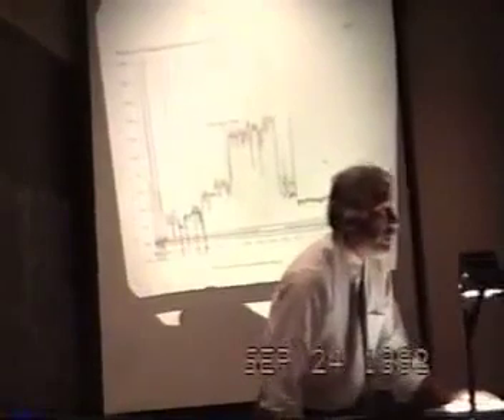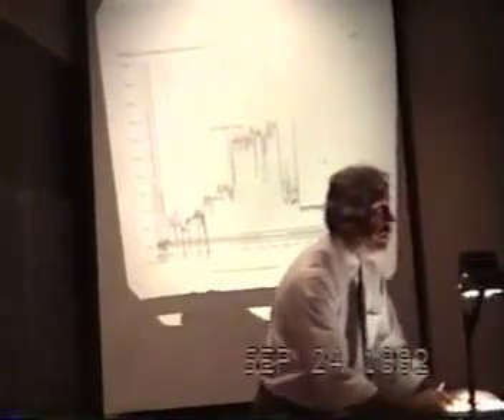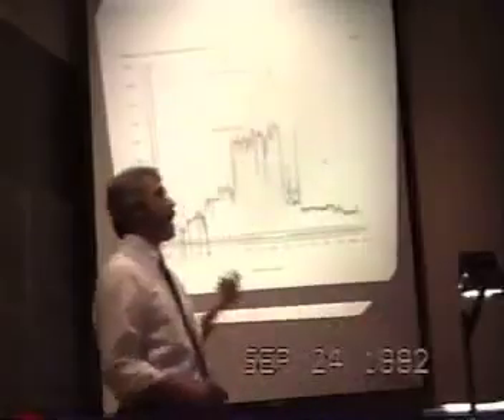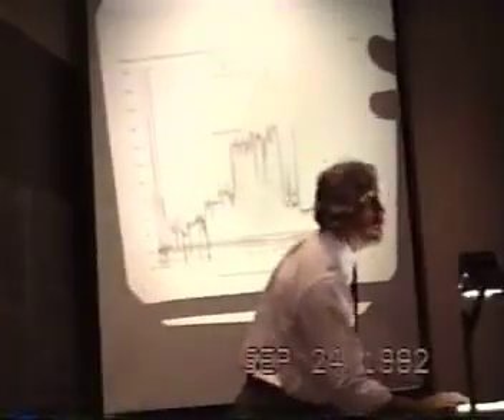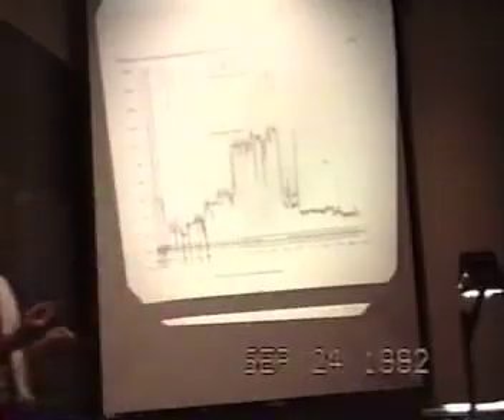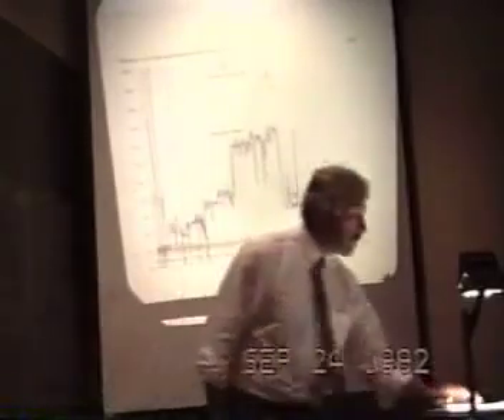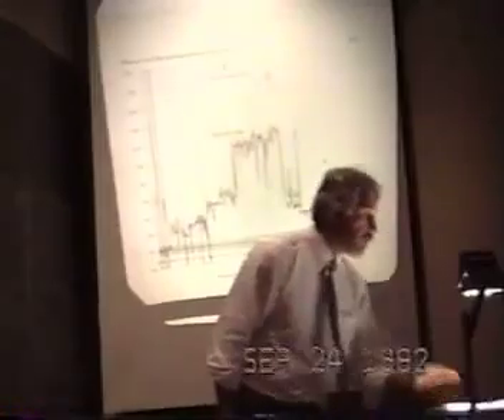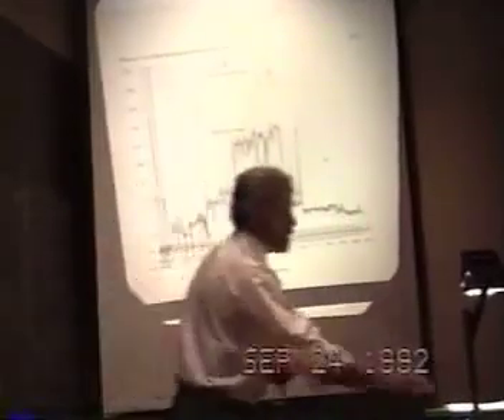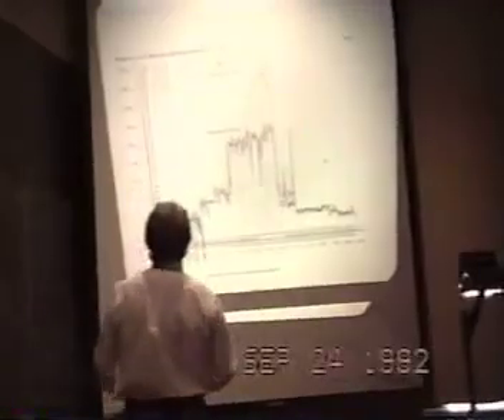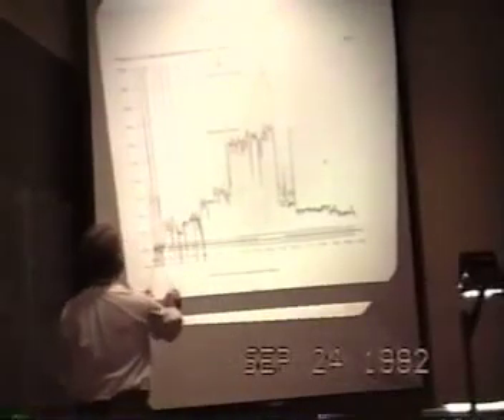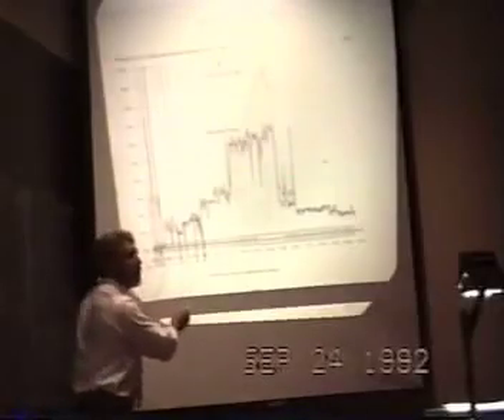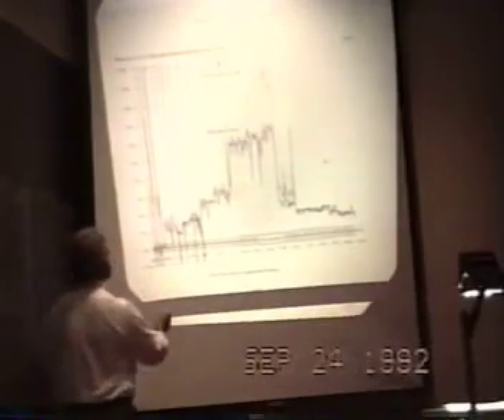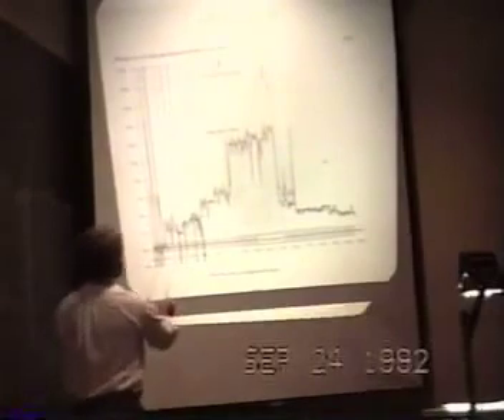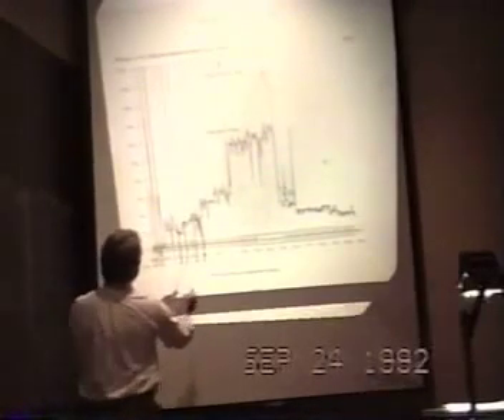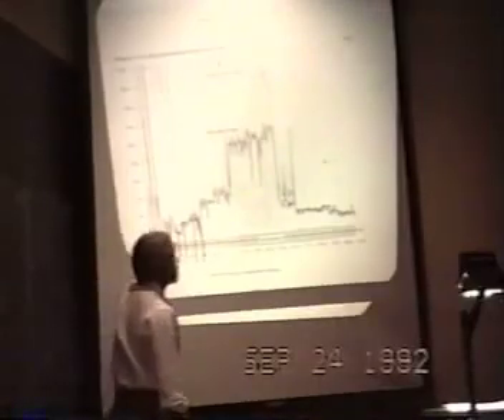This was a time in which we had prepared the calorimeter to be ramped. The calorimeter was set at 14 watts of total power, whereas there was very little electrochemical power because the electrochemical current was only 0.1 of an amp. If we normalize the observation in this case to the total power, however, because we had 13.7 watts of heater and 0.3 watts of electrochemistry, the normalization of the excess power observation to total power is a small percentage. And here we have the measurement uncertainty reflected.